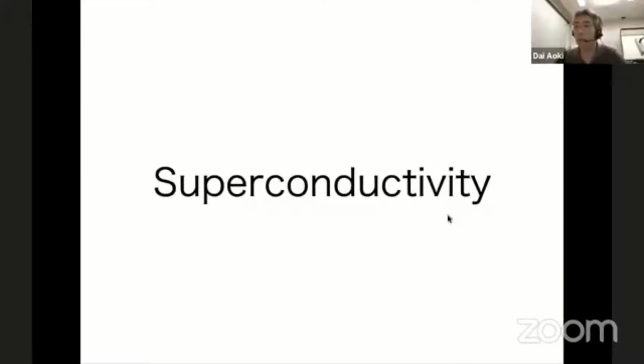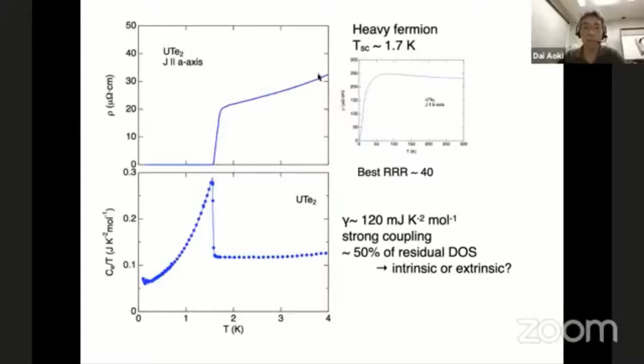Okay, so now I want to show you the superconductivity. This is a resistivity curve at zero field. Here you can see this resistivity curve shows a typical heavy fermion behavior, and at low temperature it shows superconductivity, and this Tc is about 1.7 Kelvin. In the normal state, it follows nicely the T-square behavior. And the specific heat shows a sharp jump at 1.7 Kelvin.